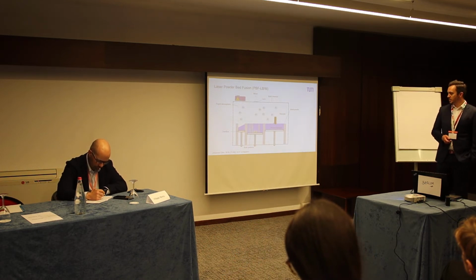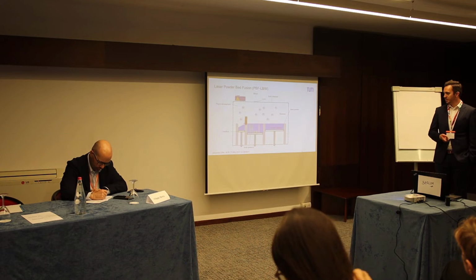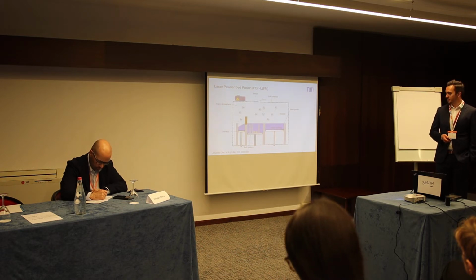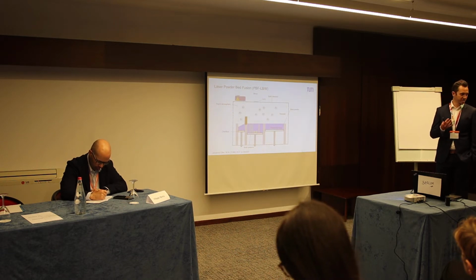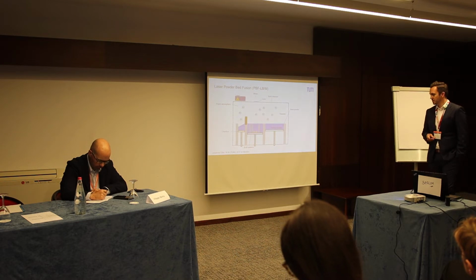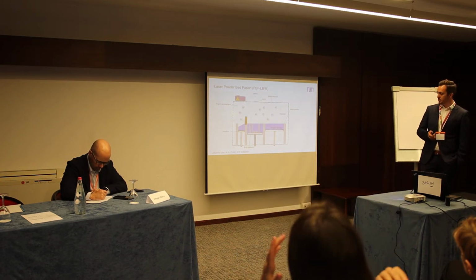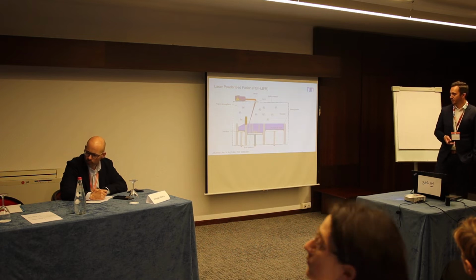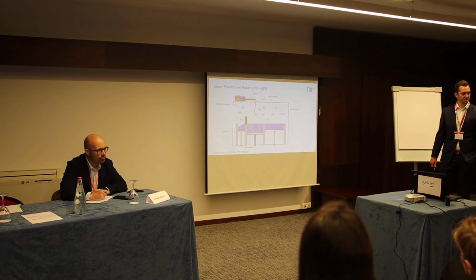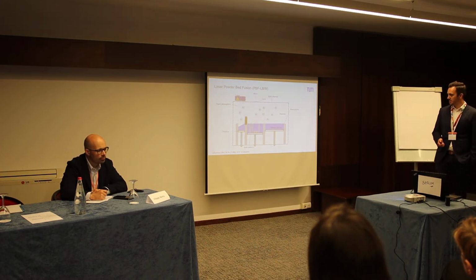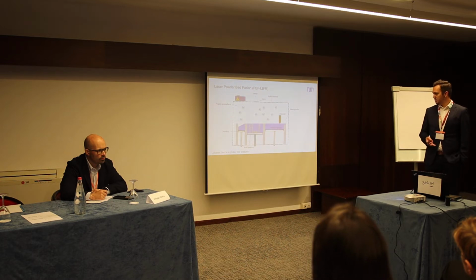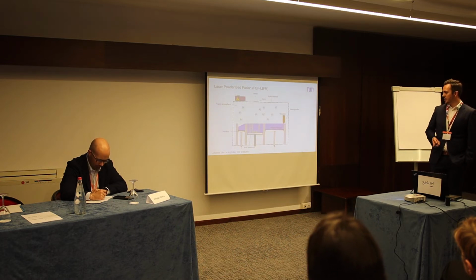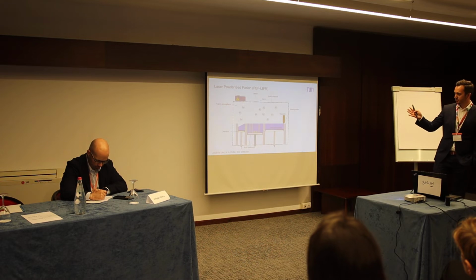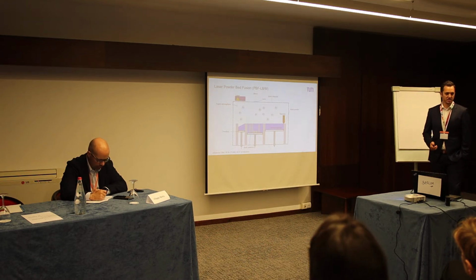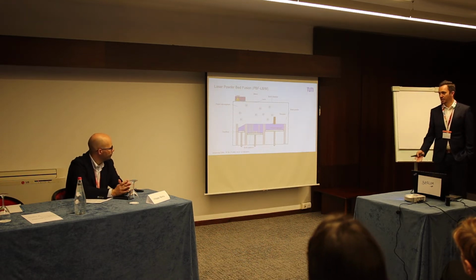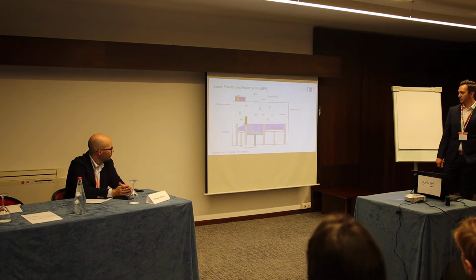So let's perform a coating process. Now we apply a small layer of metal powder on the build platform, usually about 20 to 40 micrometers, depending on the machine you're using. And then we're performing the melting process. This process is repeated until the part is finished, meaning that the recoater is going to the right, the powder storage is going up, the build platform and overflow container are going down, and another layer is being put on, and the laser is doing this until the part is finished.